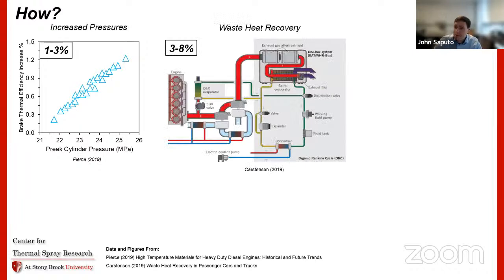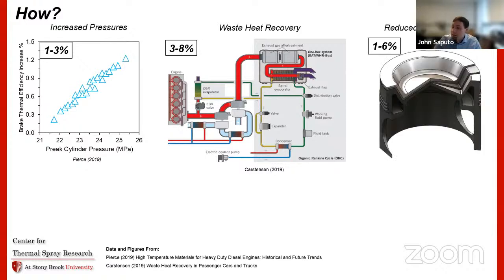A secondary thing is waste heat recovery, which is projected to be about 3 to 8%. This is kind of a busy picture, but on the right hand part of this image, they're using a volatile organic compound that's heated by exhaust gases to produce additional power from what would normally be waste. And then a third option is to reduce the thermal losses in these systems. I'm showing a section of a piston with a thick ceramic coating on top that could possibly be used to keep heat in these systems and produce beneficial work.